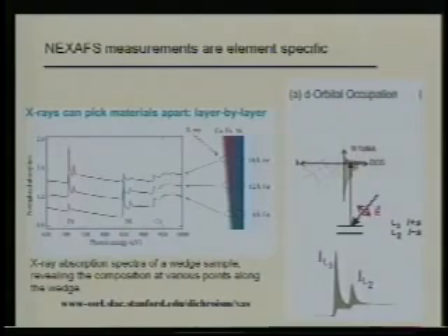So the one key that I just mentioned there is NEXAFS measurements are element specific. Here's a wedge sample that has cobalt, iron, and nickel, and it's taken at 3 different regimes. If we go from the top to the bottom, at the top you can see that you have a fairly strong iron signal, in red, because the iron layer is quite thick. The cobalt layer is the same thickness the whole way through, so you can see in the 3 plots along the wedge, it's the same intensity. And then you can see that the nickel signal, because this is done in electron yield, is actually changing, even though the nickel layer is not changing in thickness. But what's going on here is the ejected photoelectrons can't get out. So basically, you start attenuating your nickel signal.